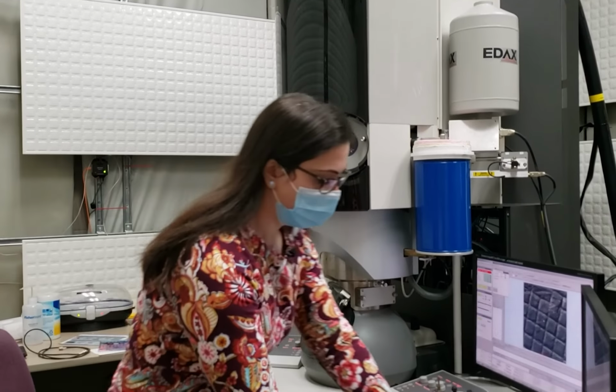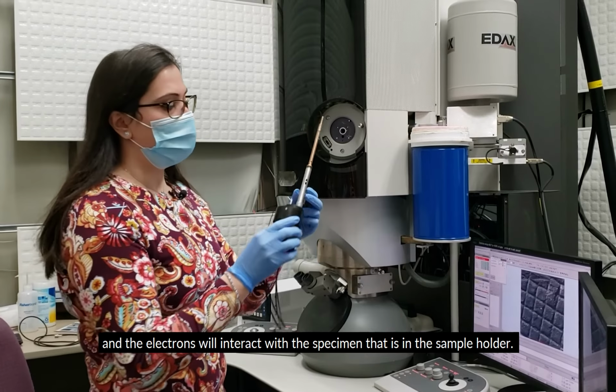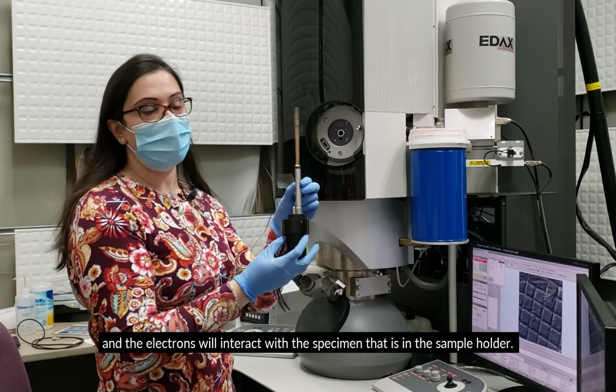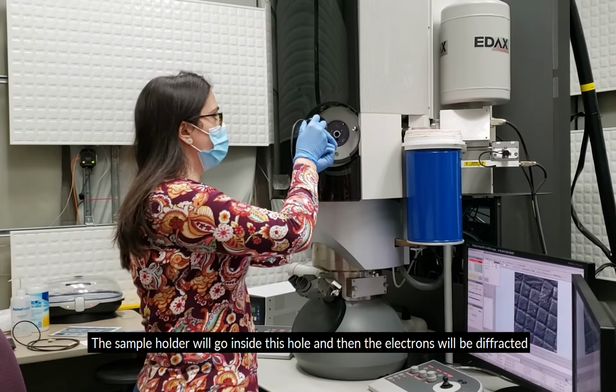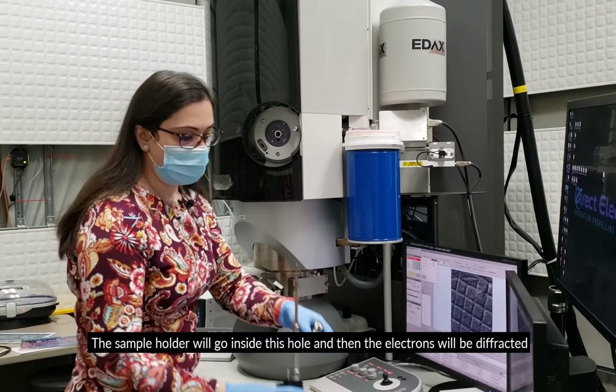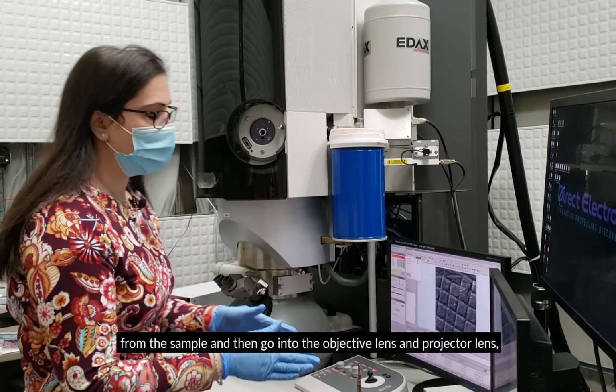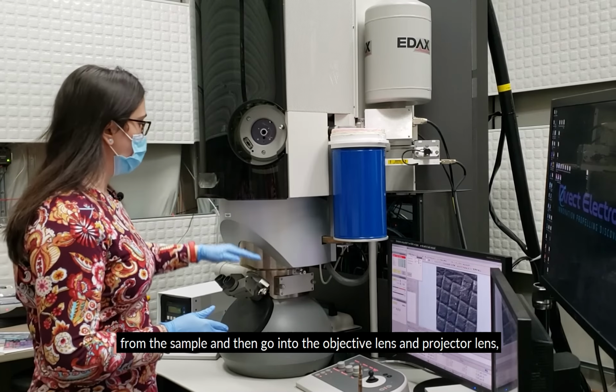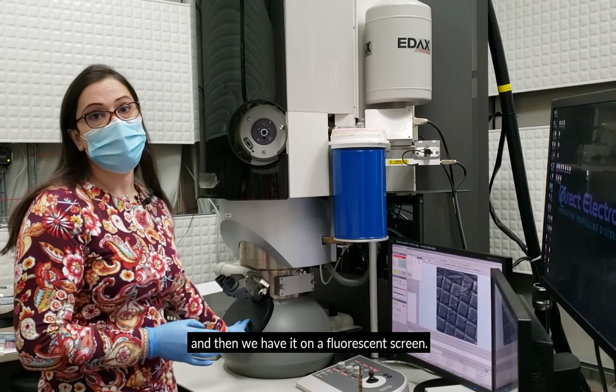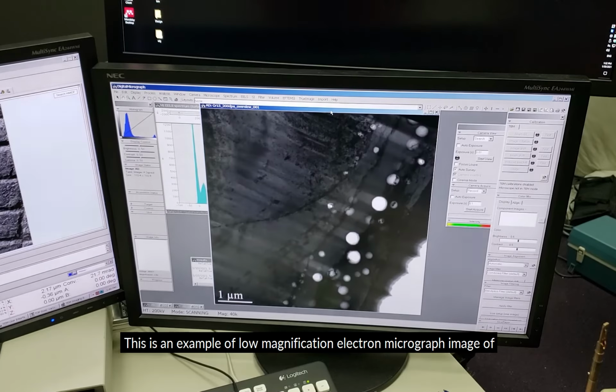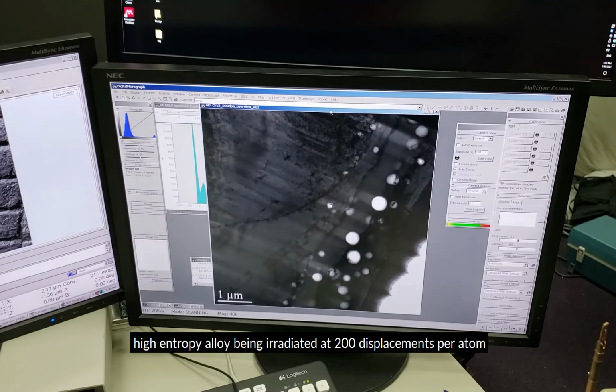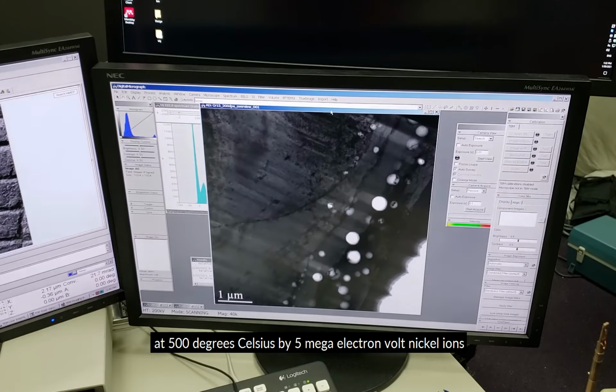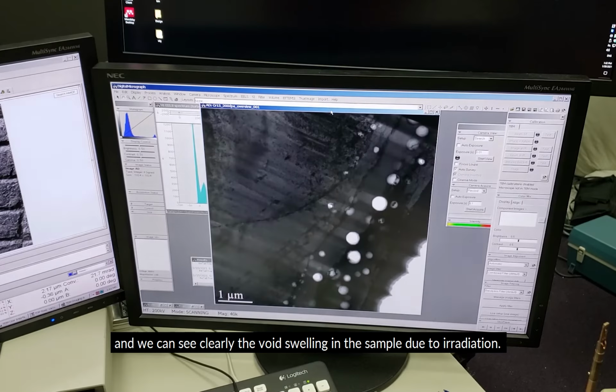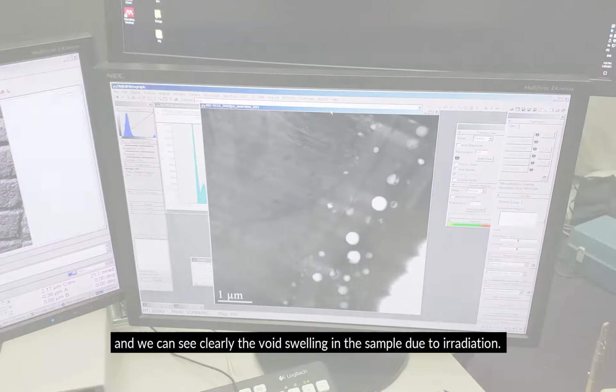The electrons will interact with the specimen that is in the sample holder. The sample holder will go inside this hole, and then the electrons will be diffracted from the sample and then go into the objective lens and projector lens, and then we have it on a fluorescence screen. This is an example of a low magnification electron micrograph image of a high entropy alloy being irradiated at 200 displacements per atom at 500 degrees Celsius by 5 mega electron volt nickel ions, and we can see clearly the void swelling in the sample due to irradiation.